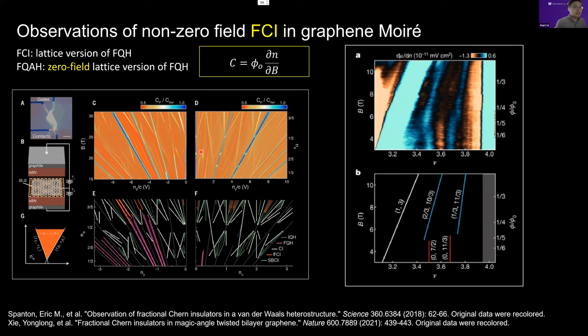So on the left-hand side is the capacitance measurement of bilayer graphene, hexagonal boron nitride, Moiré superlattices, subjected to very strong magnetic field as high as 25 Tesla. What we can see is that there are lots of line-like structures with linear slope if you change the gate or the carrier density of the system. As you change the carrier density, you meet those incompressible states, which you need to put some energy to put one electron in. That's actually the definition of insulating states.